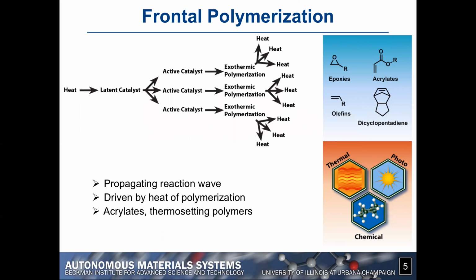It's been shown to be applicable to a range of material systems, as you can see on the top right, from epoxies to acrylates. Now, the system that we decided to adopt first is dicyclopentadiene. The reason for this is that we had a lot of familiarity with this particular system, because that's the one we had used previously in making self-healing materials. That's the healing agent that we had decided to adopt. And so that's the first polymer system that we've adopted.